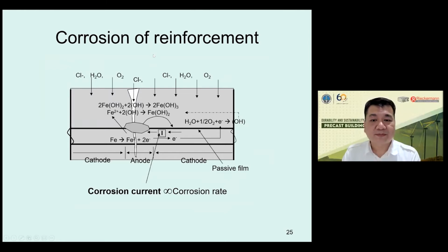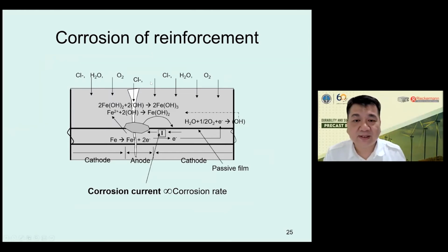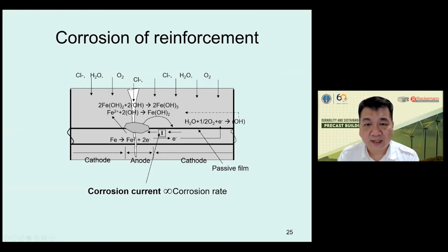When the corrosion of the reinforcement occurs, in this case, the chloride enters the rebar. So this is the corrosion condition. We have anodic condition and cathodic condition. There's a movement of electrons, and then the rebar will start to corrode. So this is the basic of the degradation of the reinforcement in the concrete.